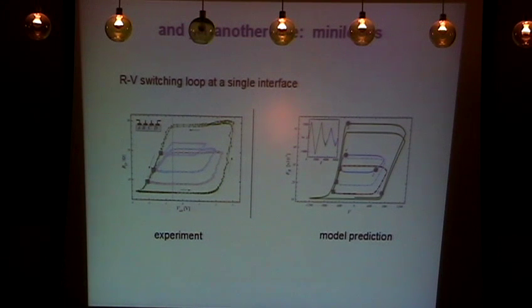Now, these electrons move in a landscape of varying ionic concentration. So you modulate the resistivity along these conductive paths, and on those conductive paths, you have just normal electronic conduction. Yeah, so what I'm saying is that the interface itself could be blocking or non-blocking. Here I just show blocking. You could just release that and allow oxygen to go out of the system or get into the system. Those would be relatively small perturbations. The goal of this is just to highlight what is crucial. So this is stripped to the bones.